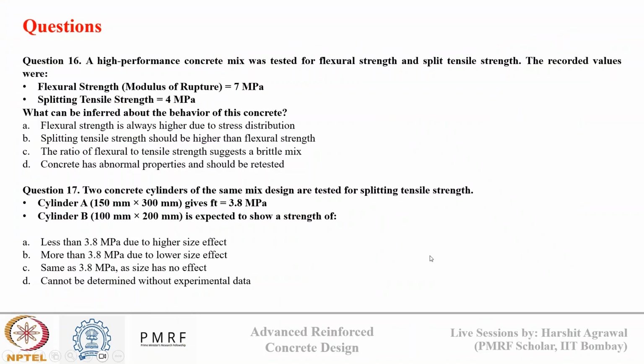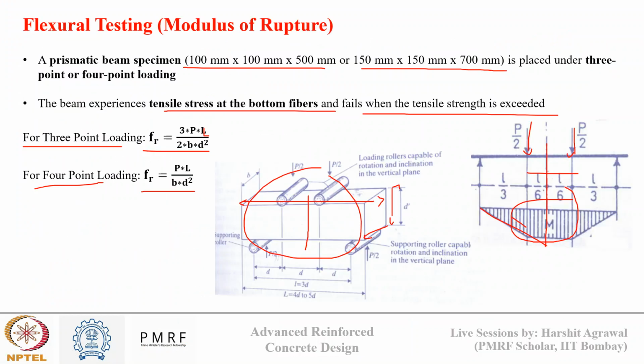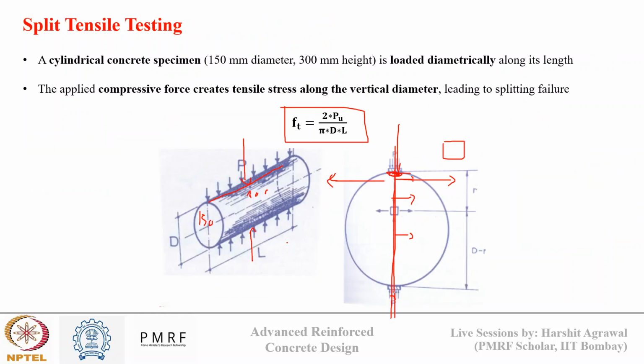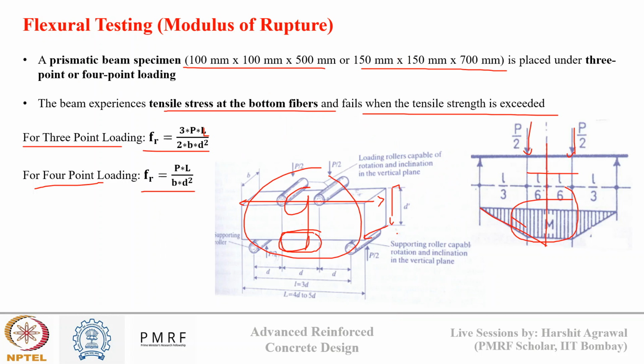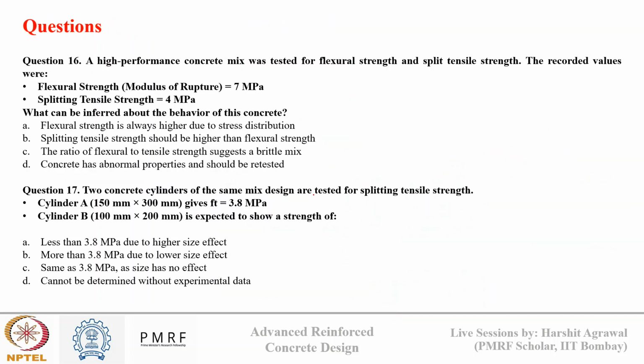Okay, so it is due to the way the loading is applied and the way stress is distributed in the system. In the flexure test, the specimen experiences tension at the bottom and compression at the top. So the failure is governed by the tensile cracking that happens at the bottom. However, in split tensile strength, the stress is uniformly distributed across the entire diameter of the specimen, and it is a more direct measure of tensile strength. In flexure, only the bottom fiber is under tension, not the top part. So that's why split tensile strength is lower compared to flexural strength, because in this the entire cross section is uniformly subjected to tension rather than just the bottom part.